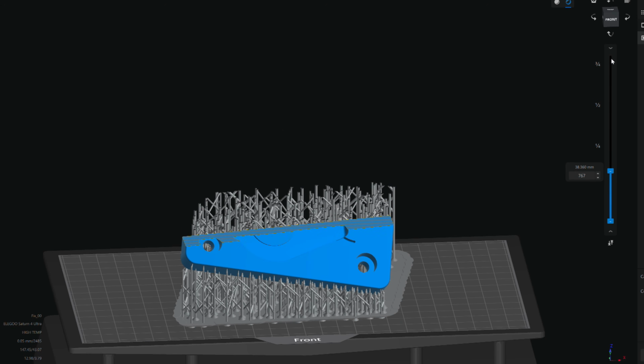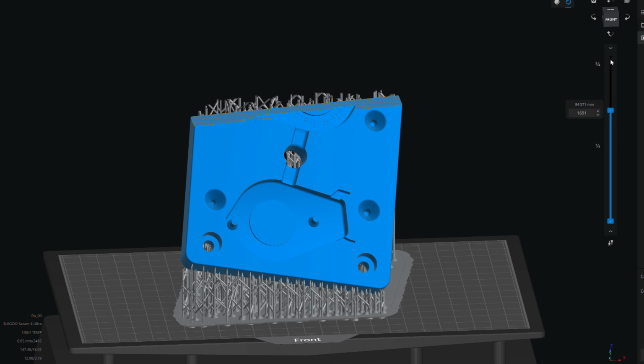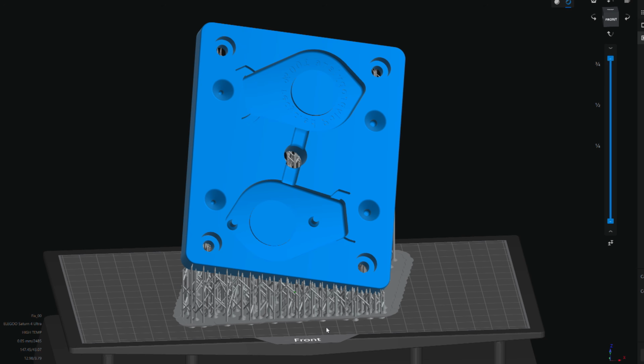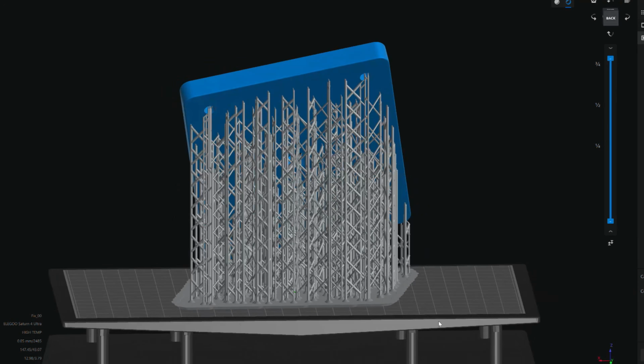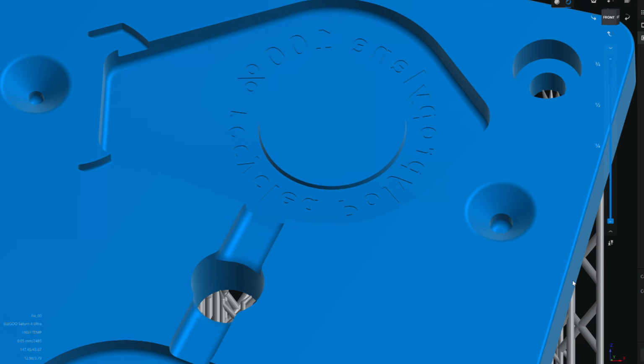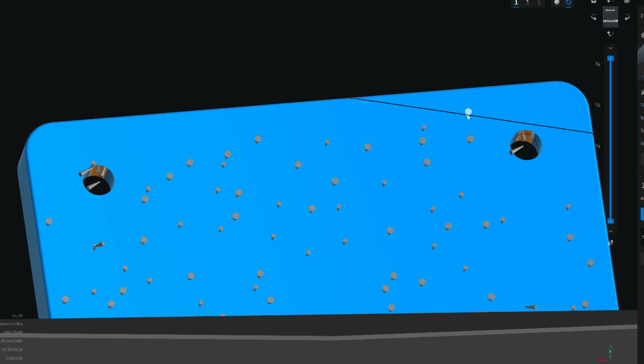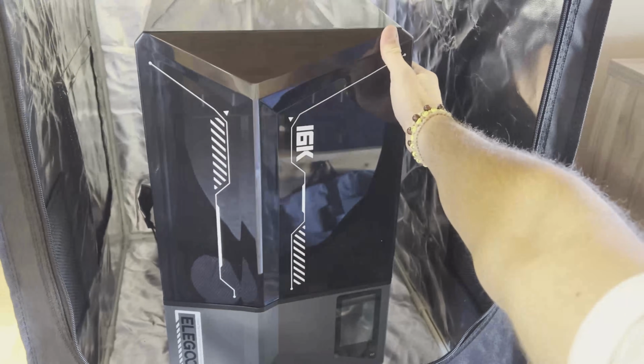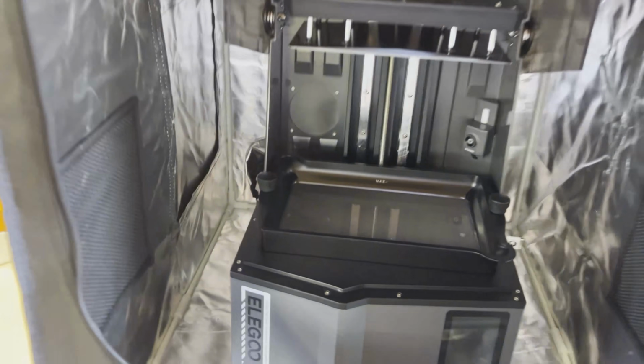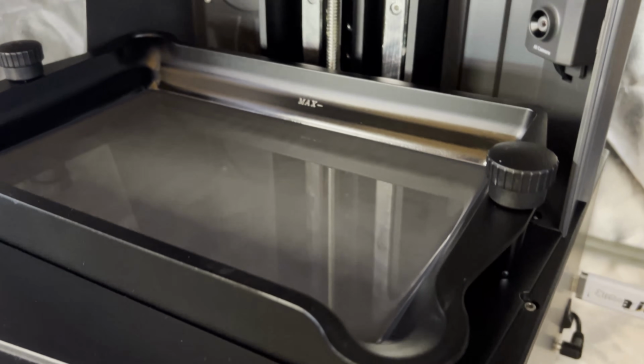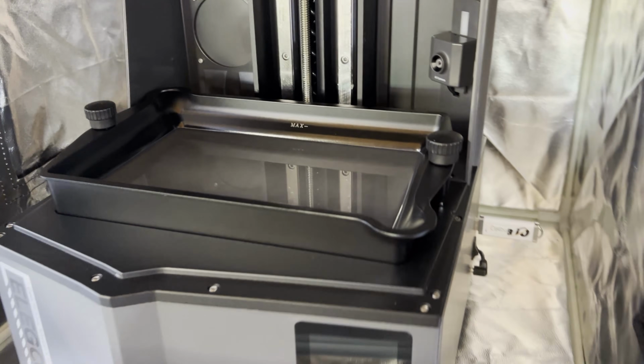I slice the mold in Chitubox and orient both halves in a way that makes sense for this design. There are no supports on the joining faces so that they stay perfectly smooth and aligned. Making this digital file into a real part is still kind of magic to me. For this one I am printing both halves on the Elegoo Saturn 4 16K using TR300 resin from Resione. This resin is specified as heat resistant up to 220 degrees Celsius, which makes it suitable for short injection runs, although molten polypropylene, which I use in the TARS machine, reaches roughly 240 degrees Celsius. So it's right at the limit.